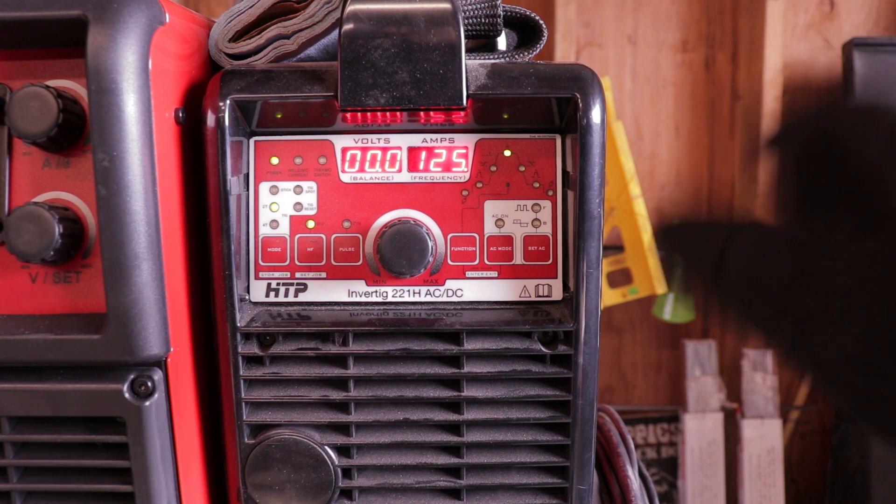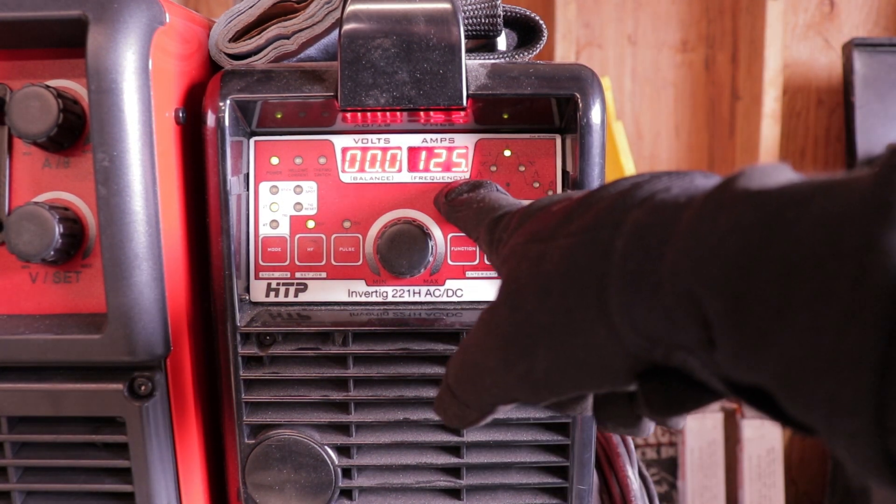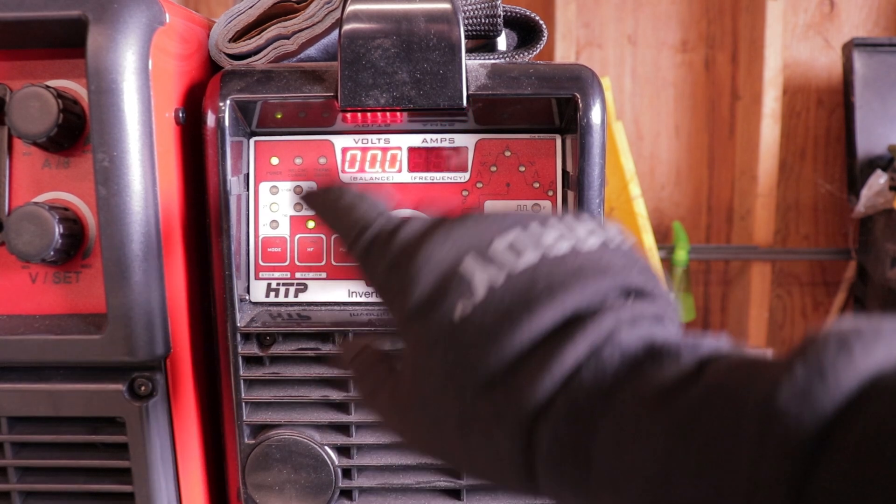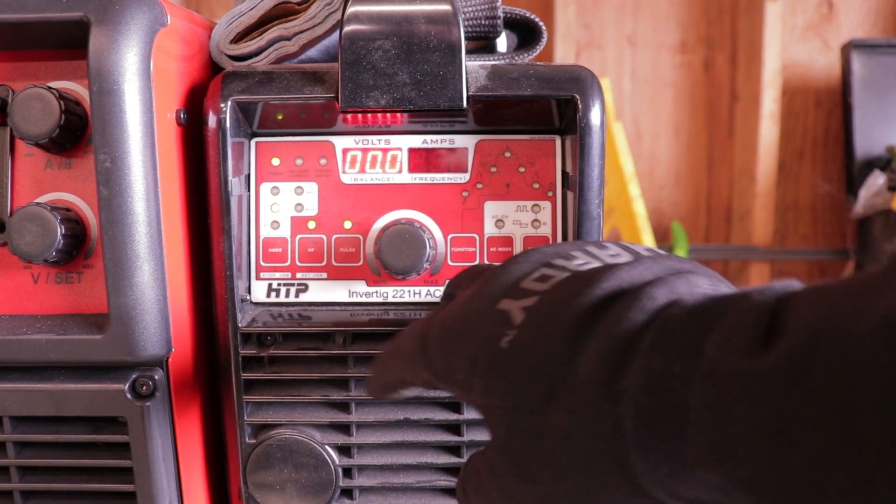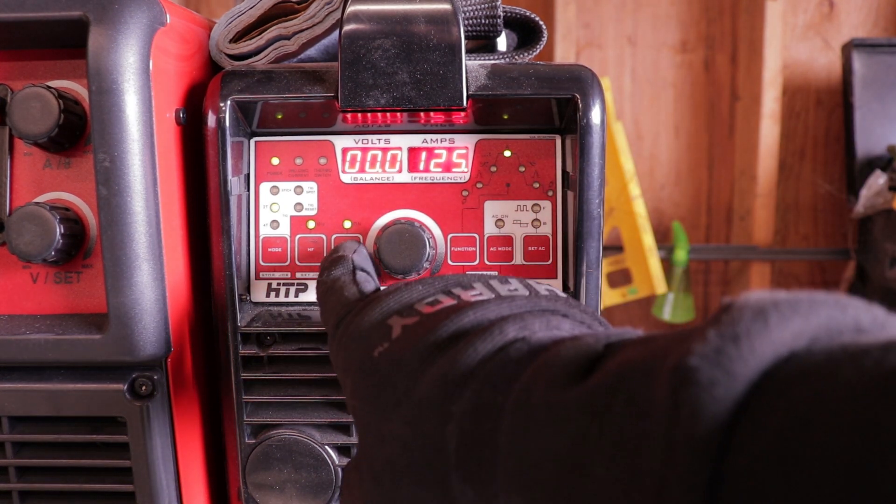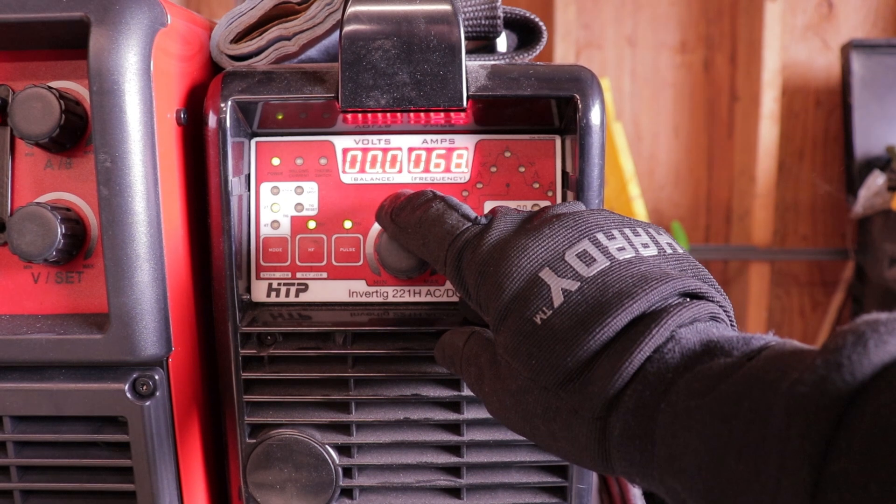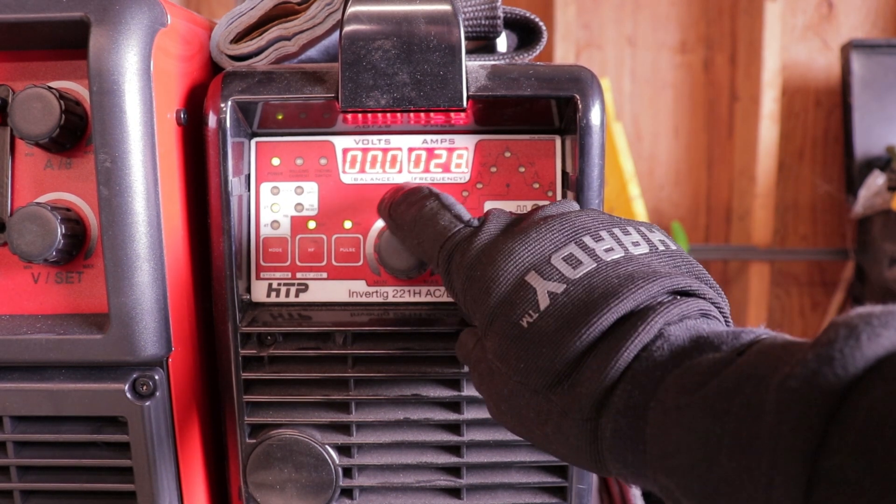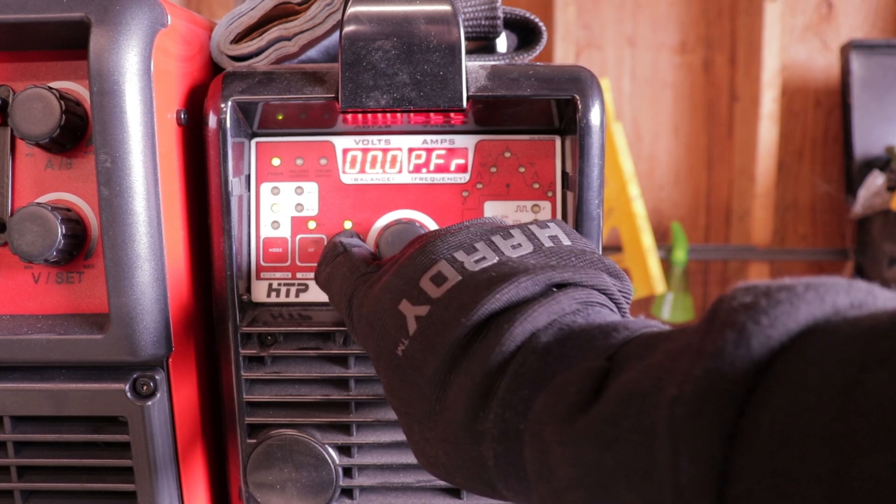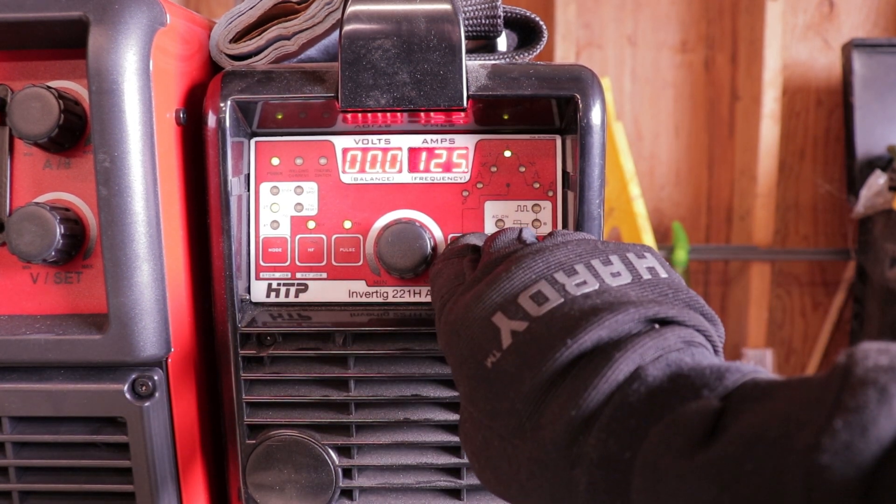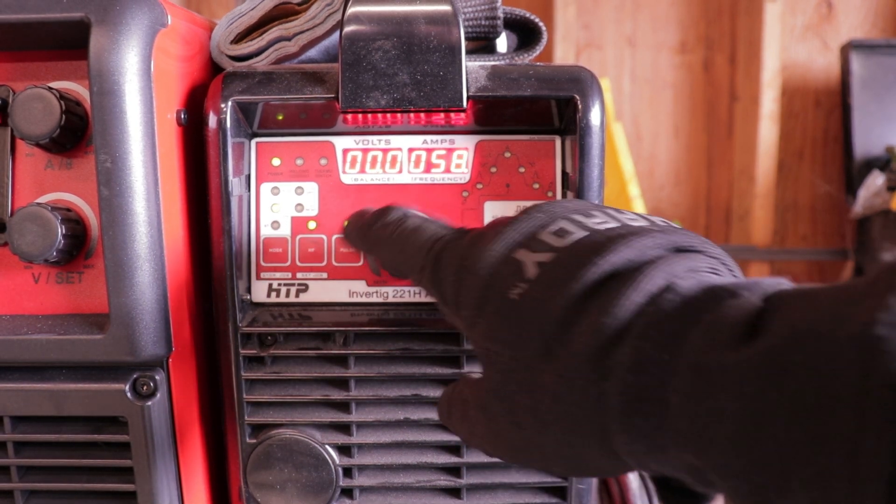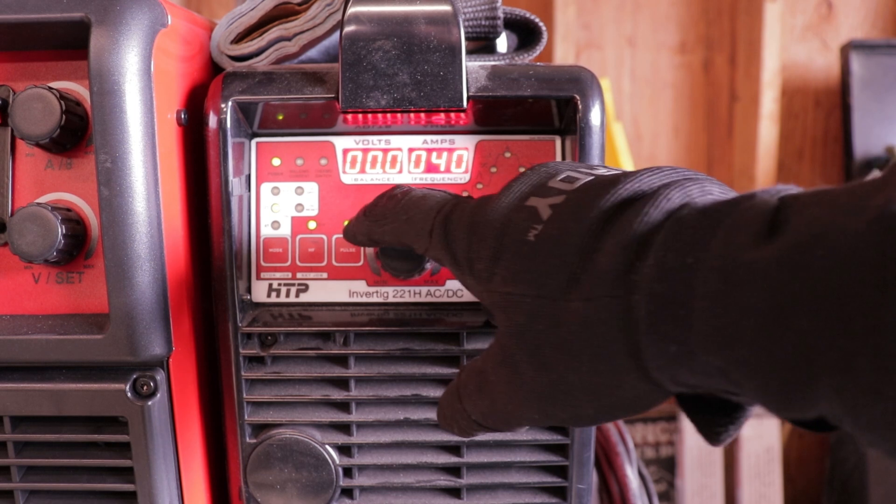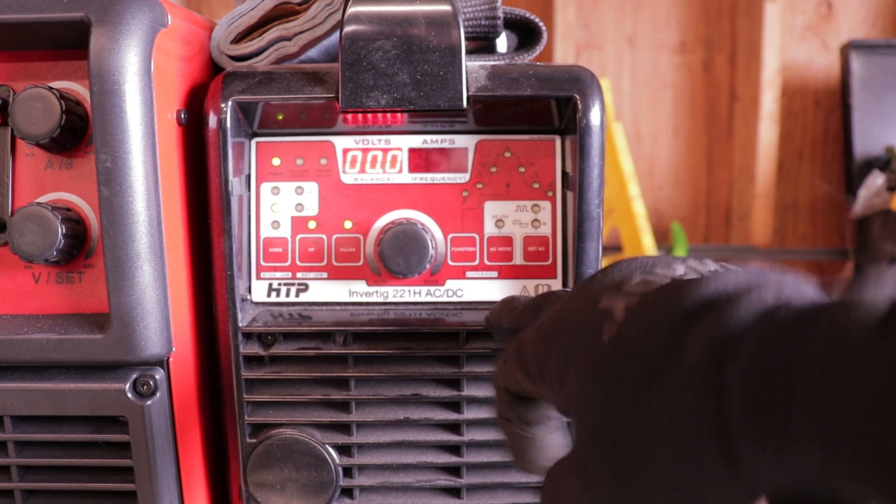For the outside corner on the 16 gauge I'm going to leave it at 125 amps. I'm going to turn on the pulse, pulse frequency. When I'm just doing autogenous I like it around two to two and a half per second. And then we're going to go, let's see, we'll just do the rule of 33. That one actually works really good. We'll go to the low side. That will be 33 also. And we're all set.